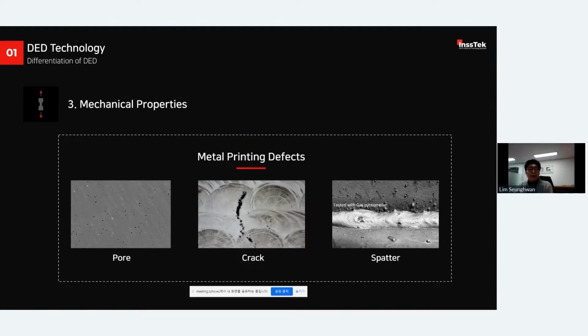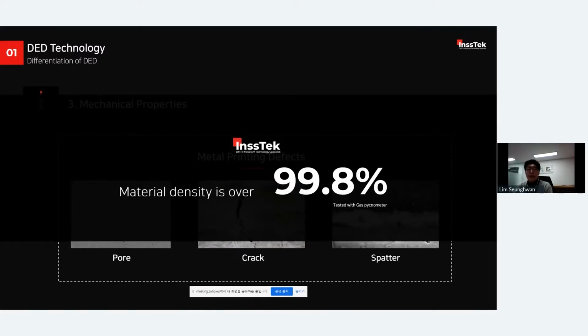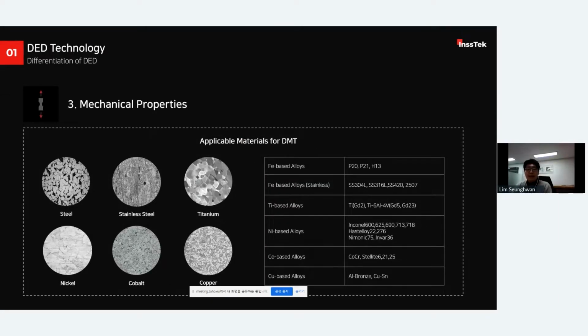These features are about some defects. During printing, process parameters should be controlled precisely so as not to damage mechanical properties or generate cracks and defects. If process parameters are not optimized, defect-like features can occur. InssTek has standard process parameters for more than 20 types of materials that are most common in industry, such as iron, nickel, and titanium. When working with a standard process, the internal density is very excellent at 99.8% or more. InssTek has standard process recipes for more than 20 types of alloys shown in the table. Various alloys such as titanium, steel, nickel, copper, and cobalt are available.